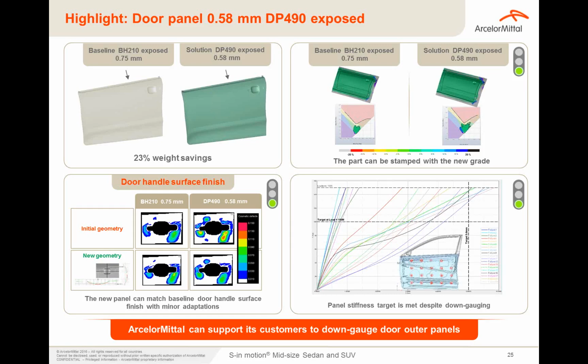The part can be stamped very easily without any issues. We checked by simulation, but we also did some prototype trials in our press shop down to 0.58 millimeter thick, and even in this very thin gauge, we had very good parts with a good surface quality and without any rupture. Surface finish around the door handle and panel stiffness were also assessed and meet the requirements, as shown on the figures on the bottom of the slide.